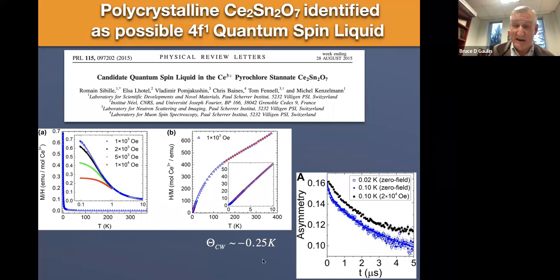Now, the Curie-Weiss constant that you would get from this is itself pretty low. This is some measure of the strength of the magnetic interactions. It's about a quarter of a degree Kelvin, but nonetheless, this is the sort of thing that attracts attention whenever you see it, because it means that this has the minimal qualifications to be pursued as a quantum spin liquid type ground state. So this is what attracted our attention.